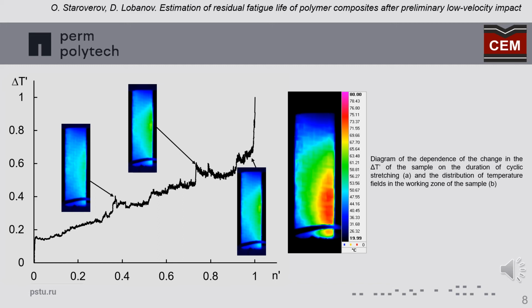In order to assess the intensity of processes of accumulation of damage, the dependencies of the change in the maximum temperature on the time under cyclic loads are considered. The delta T value was determined as the difference between the current value of the maximum sample temperature during cyclic loading and the initial one. By summing acoustic emission signals, the values of cumulative energy were obtained, reflecting the degree of accumulation of defects in the material under the action of the load during the entire test.